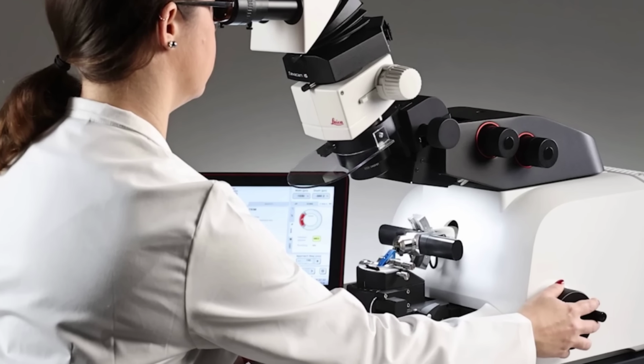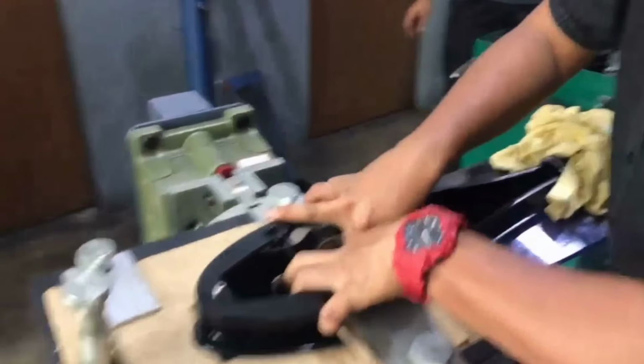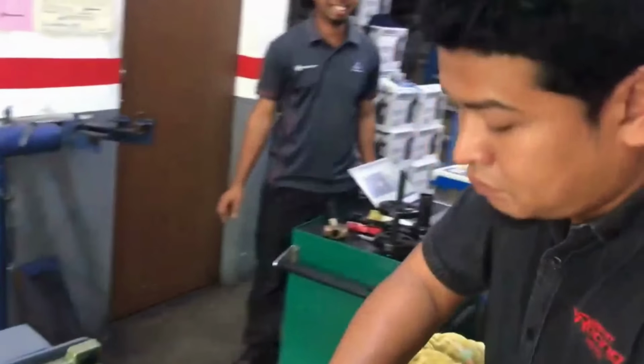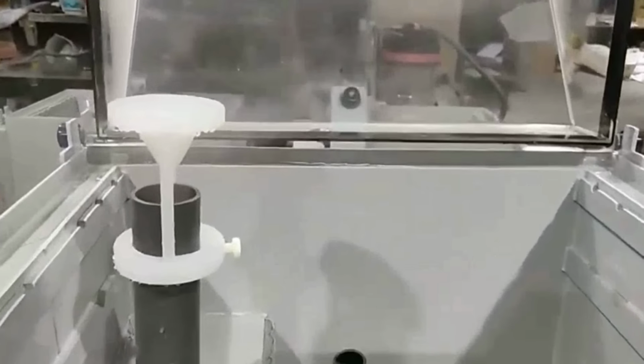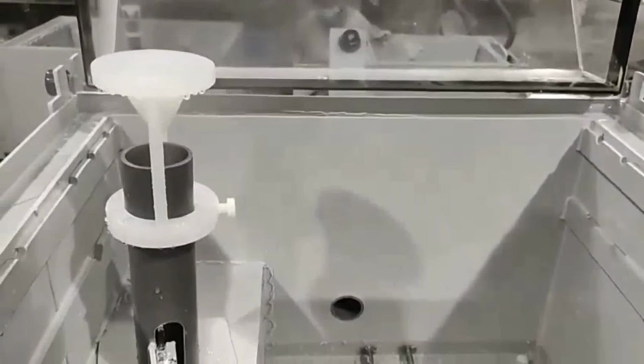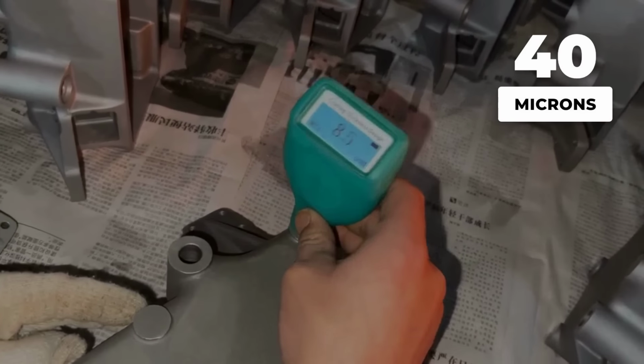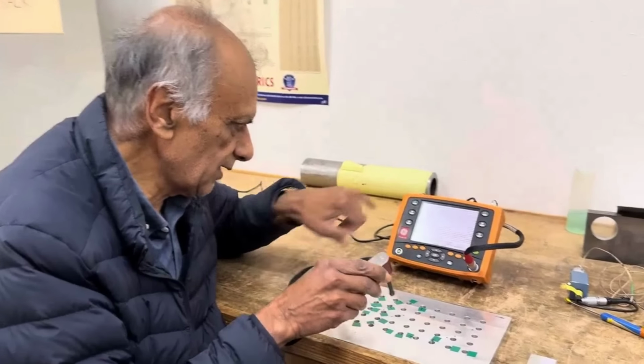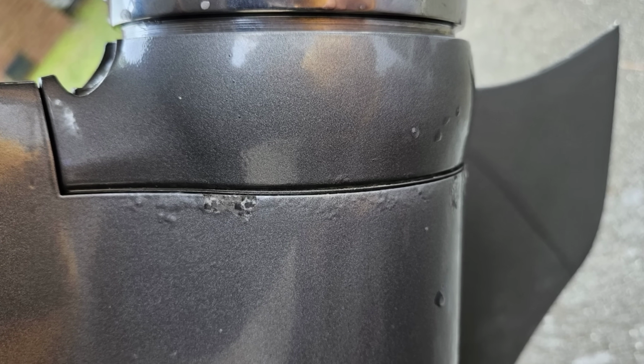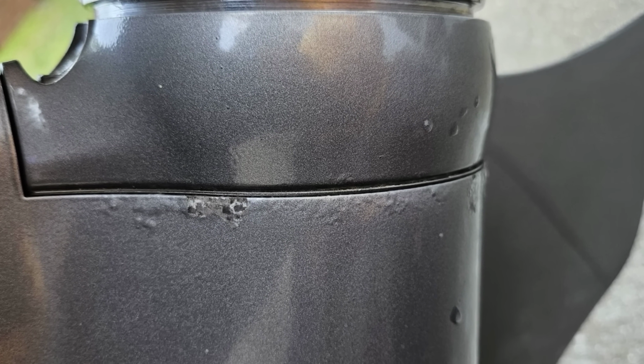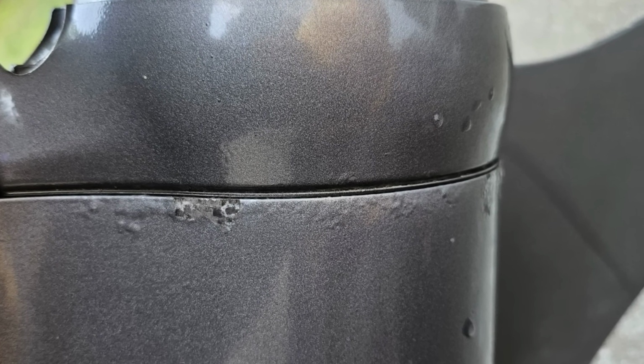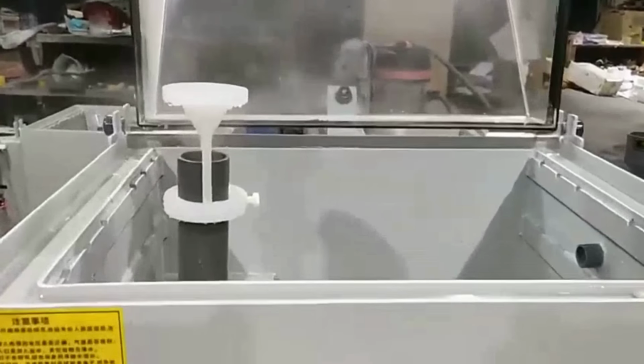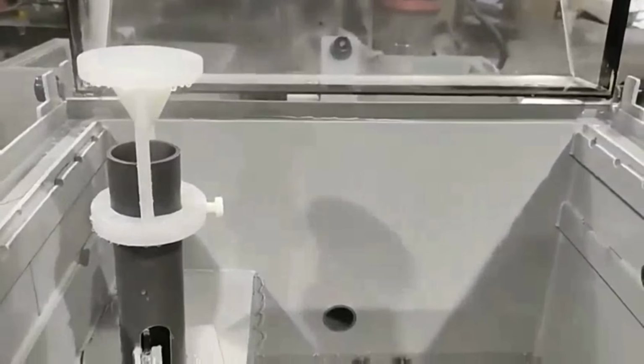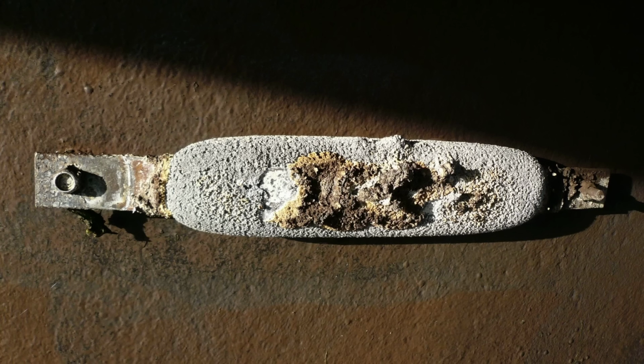Surface protection tells another story. The Mercury lower unit gleams with a thick Type 3 hard anodized finish, built to withstand years of brine and UV. Coating thickness measures over 40 microns, confirmed by eddy current probes. Under the microscope, the Chinese lower unit powder coating appears thin and uneven, flaking at edges and exposing raw metal after simulated impact. Salt water accelerates the damage, pitting spreads, fasteners rust, and sacrificial anodes shrink faster than designed.